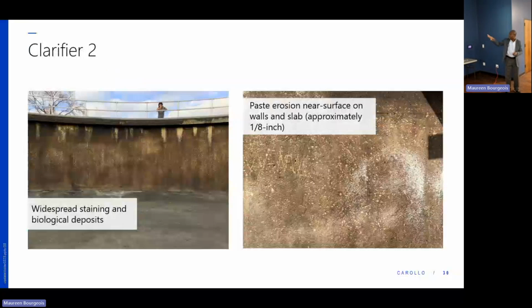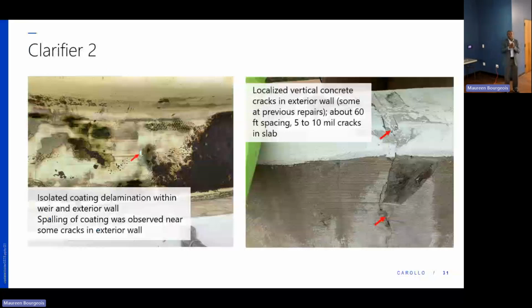At clarifier number 2, though, it was coated. So we looked at the coating, and some of the coating is delaminated. Delaminated is where the coating is beginning to come off like a sheet because the bond is no longer there to hold it. And so we saw that on clarifier number 2. And also spalling of the coating was evident in some of the areas where the wall was cracked. We see a sample of the crack of the wall. This occurs about every 60 feet. You see that localized vertical crack, and we captured that also.